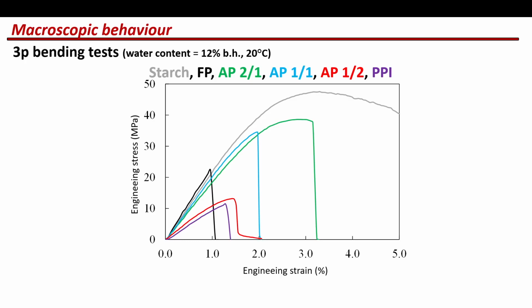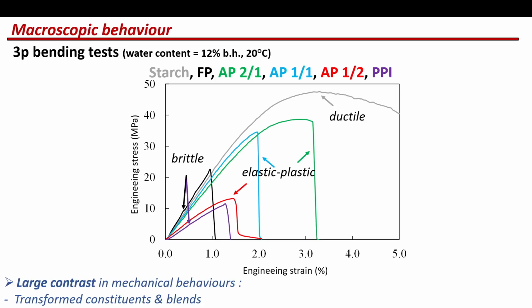This is a typical engineering stress, engineering strain response for a 3-point bending test under a water content of 12%. As you can see here, we move from a ductile behavior for the starch material to something that is more elastic-plastic behavior for the composite materials, down to a brittle behavior for the flour and the protein material. To comment on this curve, we can see clearly that there is a large contrast in mechanical behaviors, which can be explained by the transformation of the constituents and the blends, and also by the various formulations that were obtained from the extrusion process.